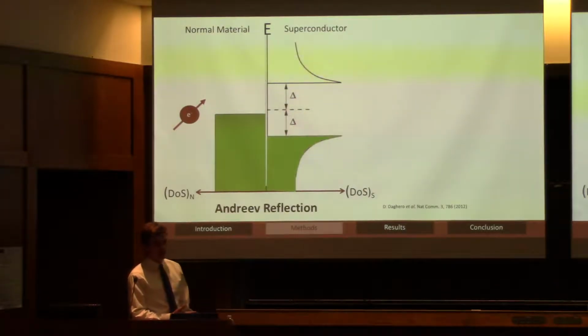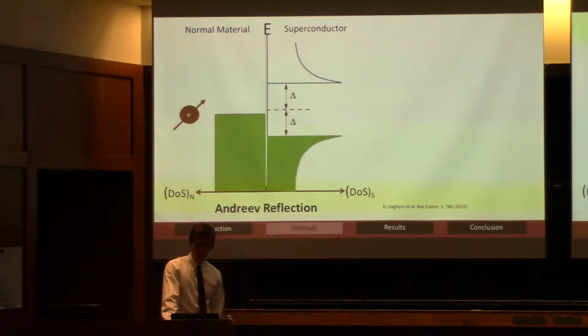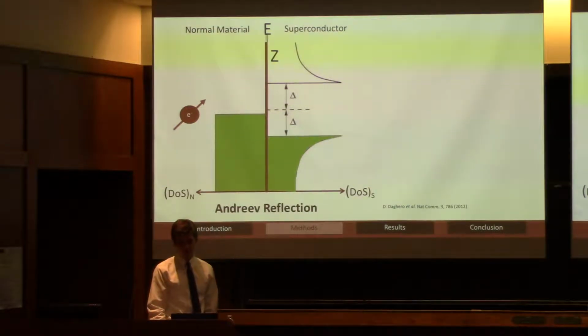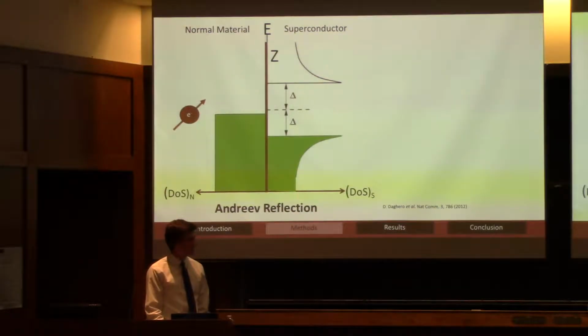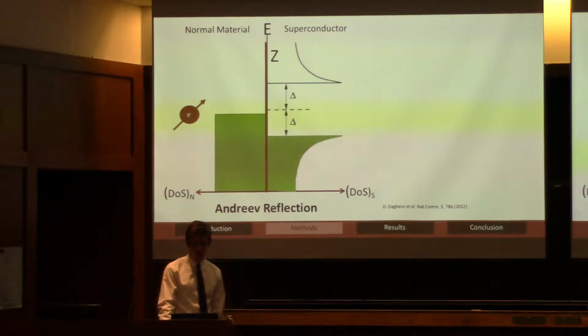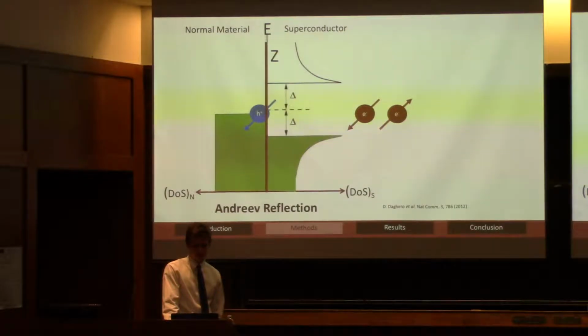On the left, you've got your wire, your normal material. On the right is your superconductor. And these are density of states for electrons. So if you have an electron in your normal material that's in the energy gap of your superconductor, it needs to get into a Cooper pair to get in there. So you have this boundary between your normal material and your superconductor. And Z here is how opaque this barrier is. So opaque meaning if it's really opaque, it's hard to get electrons in there. If it's really transparent, it's easy. So as this electron comes into your superconductor, it picks up another electron, forms a Cooper pair, and you get a hole that's reflected on the other side in your normal material.